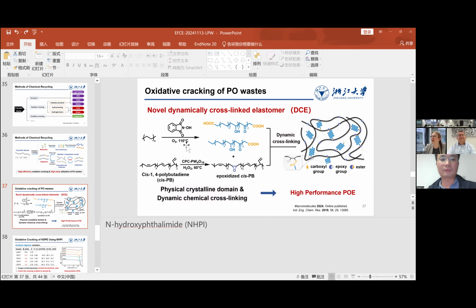Okay, so you're working in the melt, I assume, or close to the melt. For this one here we use a little bit of solvent to dissolve it, but right now we can do this in aqueous solution, in water, with a different catalyst. We developed a new inorganic oxide catalyst that can do the oxidative cracking of high density polyethylene in water in 2 or 3 hours, and we can still get oligomers with a molecular weight around 2 or 3 thousand grams per mole. But for this work here, we do it in solution. We use an organic solvent to dissolve it first.